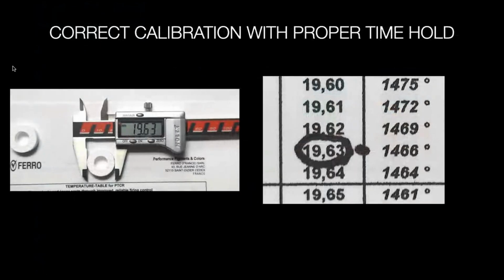and I put down 1450, which is what the temperature for the VITA ST material is. So I put the ring in there and I ran it up and I left it for what they told me to leave it, which was 1 hour. And when I brought it down, I measured it and it measured 19.63. And so that is my standard for VITA ST. I know that if that ring comes down and it shrinks from 20 millimeters to 19.63, I'm going to be around 1460, 1450, okay? So if it comes between these, I'm happy. I've never gotten one to go exactly to 1450, but it's just a matter of tinkering with it.